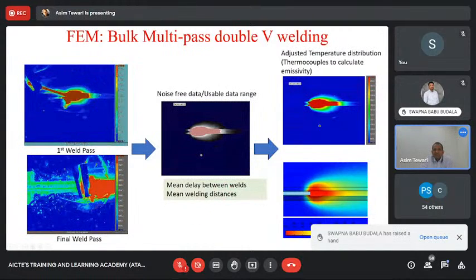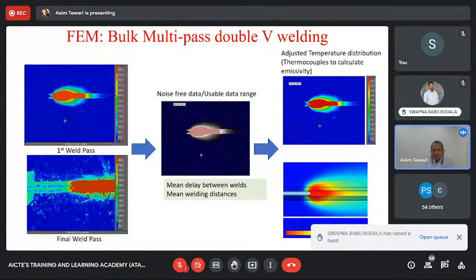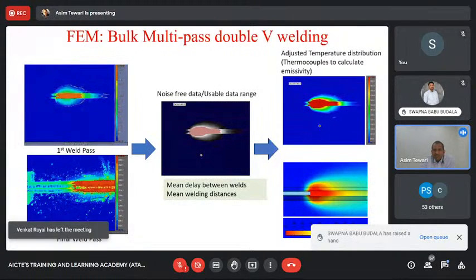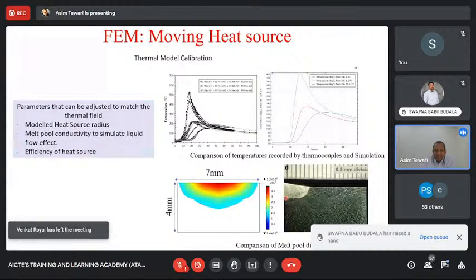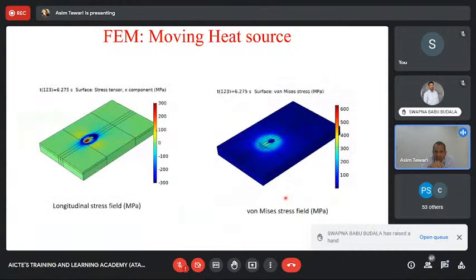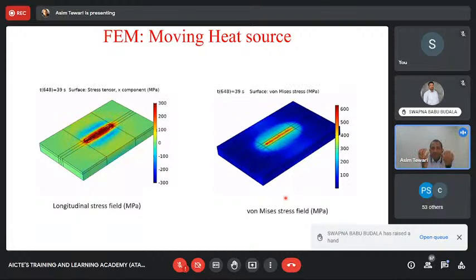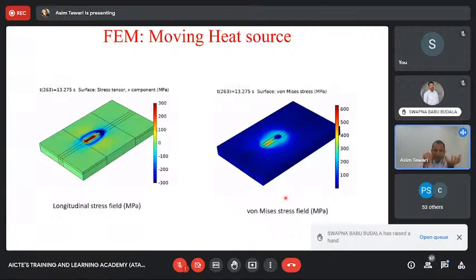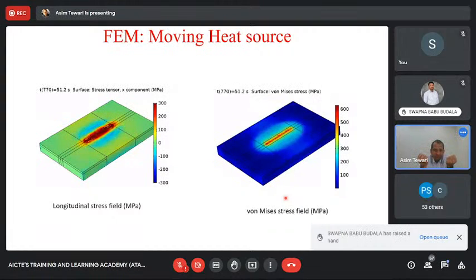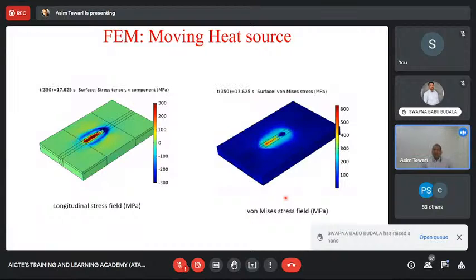And when you do the same through simulation, you can see how the temperature variation is actually occurring. So you can exactly see the temperatures from this and this, which is simulation, and map it with the experiments. What I'm trying to tell is that we now have a very powerful experimental tool which is used to validate our multiphysics numerical models which we have developed. Now these two put together would provide you the understanding of the residual stress formation.